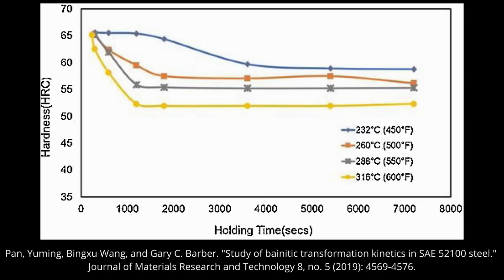You can also just let it cool in air after the Austempering. So they held it for a brief amount of time, no bainite formed, then they let it cool after that, and they formed all martensite. And so they're all around 65, 66 Rockwell because it's fully martensite. This actually has a name.